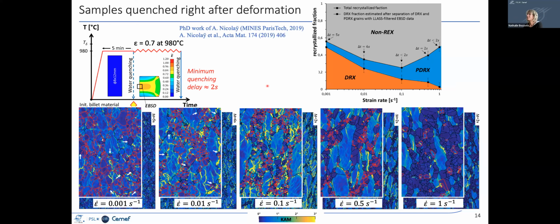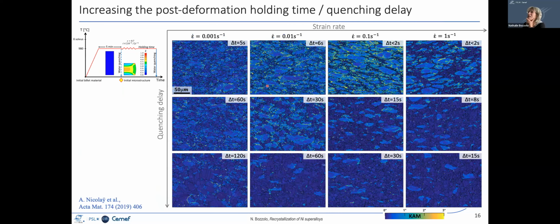All right. Now, this is an overview of post-dynamic recrystallization kinetics depending on the strain rate. You have 4 values here, and with increasing the quenching delay. So this is kind of an overview of the post-dynamic recrystallization kinetics. And of course, the recrystallization progresses with increasing holding time, no wonder. It also gets faster and faster with increasing the strain rate as a result of higher driving force and higher temperatures. What I would like to emphasize here is the typical times we are dealing with.